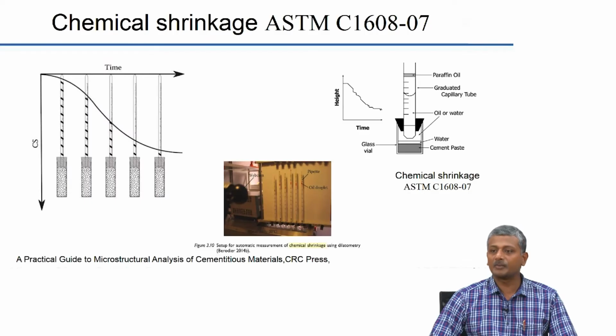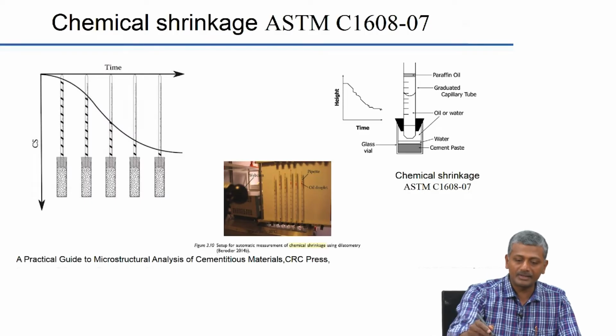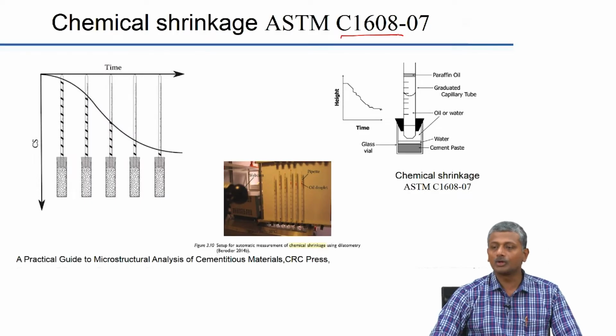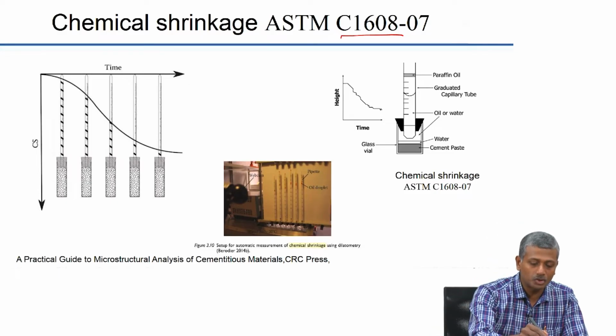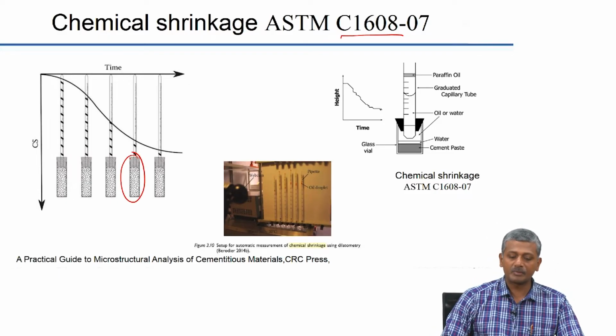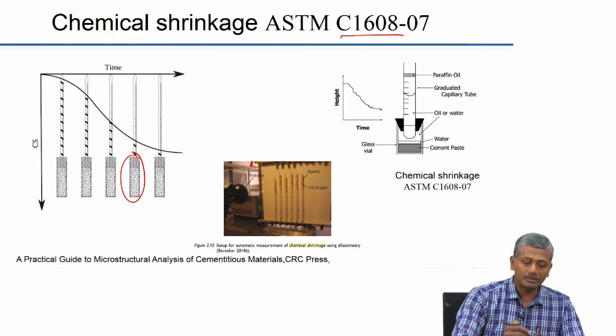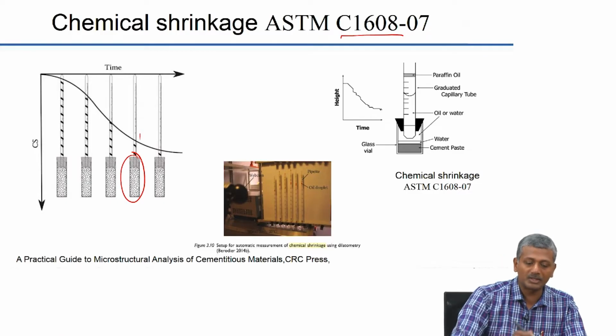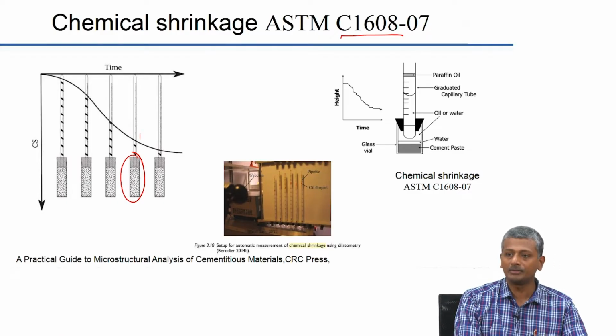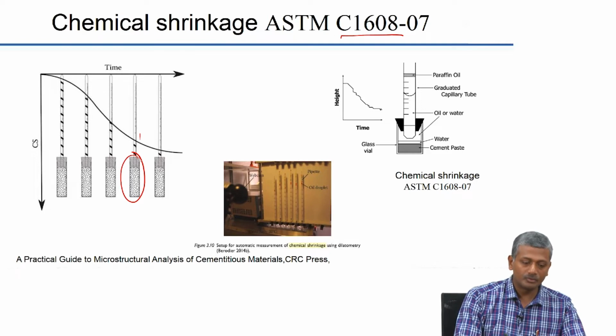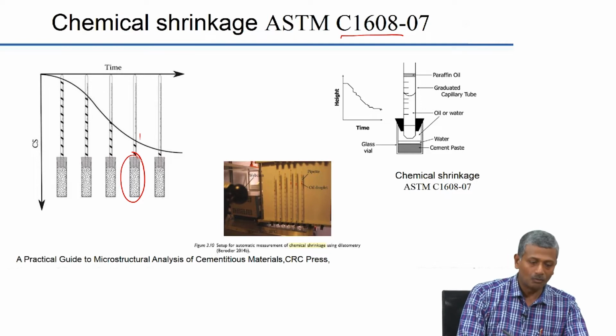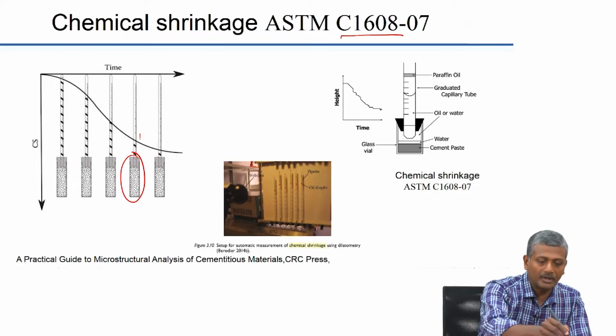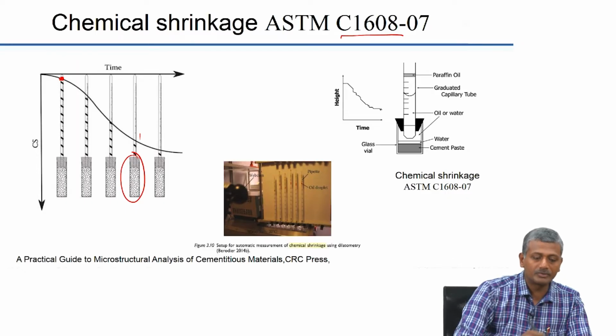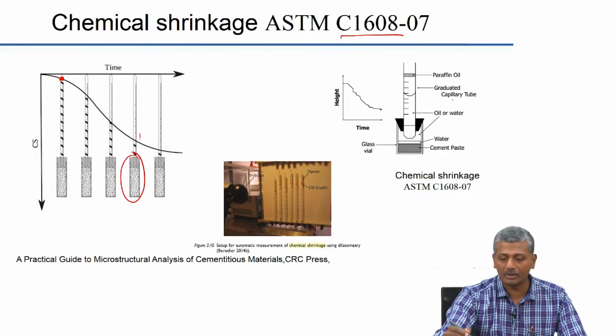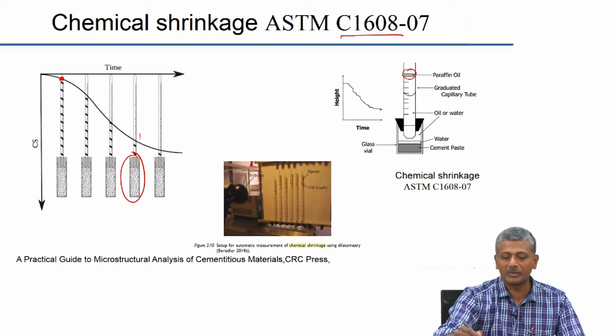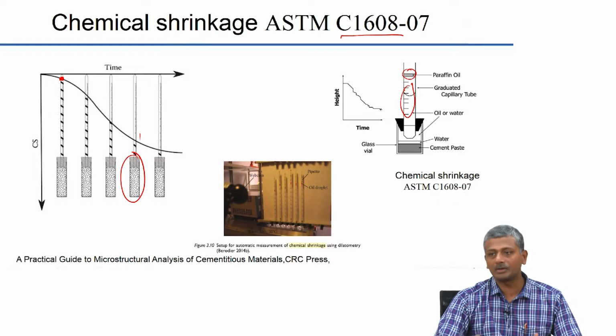This is an experiment again which has been standardized now in ASTM C1608. So, all you do is simply have a vial in which you put your mixture of cement paste and water, and you have a tube, a graduated tube which is connected to this vial. Okay. You fill up this tube with water till the top, and then you have a droplet of oil which is kept on the top. So, there is an oil droplet which is kept on top, which does not mix with this liquid here, which could be either oil or water.